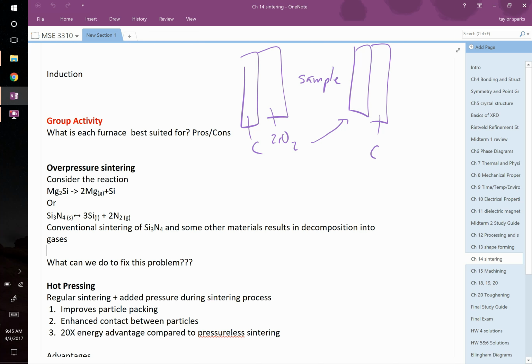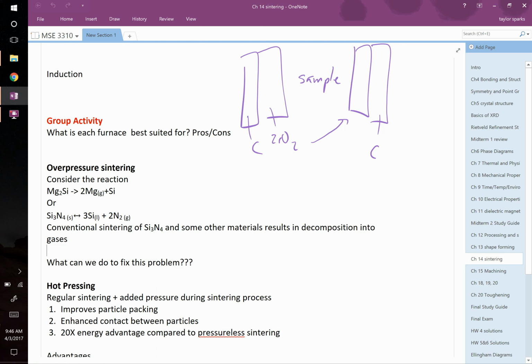Le Chatelier's principle means that if you've got reactants going to products, and you pack the house with lots of products, then you make it less likely for them to form, right? So if you want to sinter silicon nitride, but you don't want to form silicon and nitrogen gas, then you put it in a chamber with as high a partial pressure of nitrogen as possible, and it will prevent this from happening at quite as low of a temperature. It'll move to higher and higher temperatures. And this can be really good if you want to prevent it from happening.